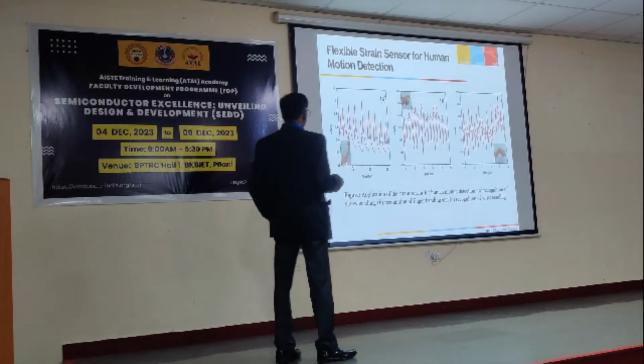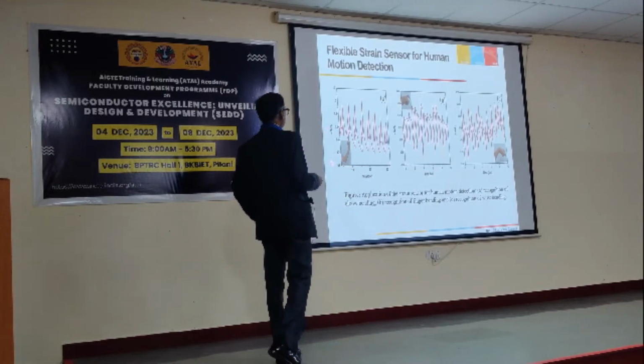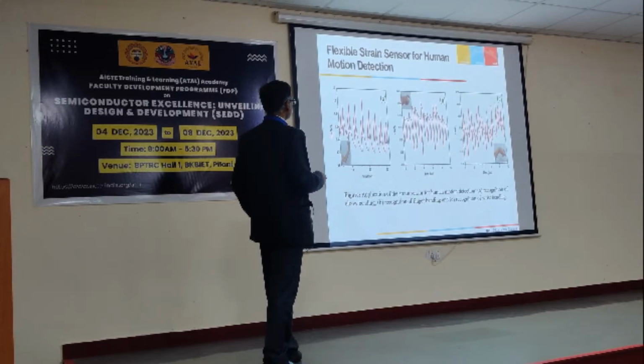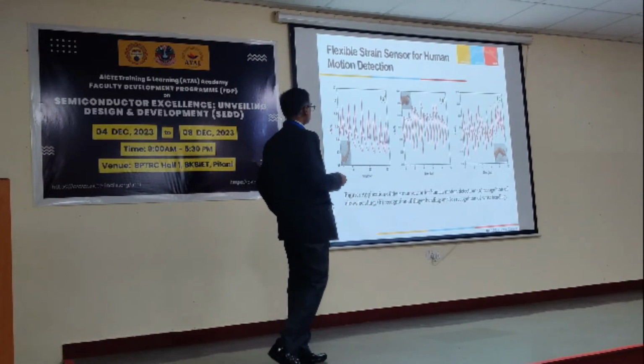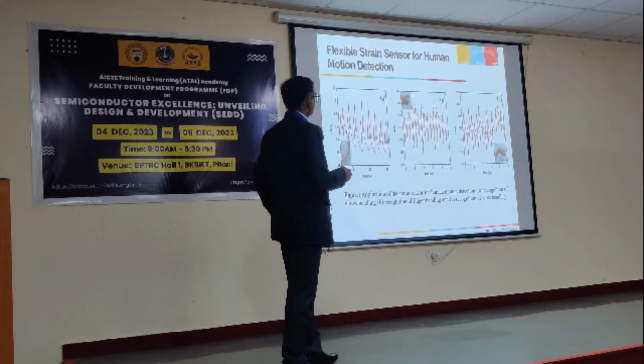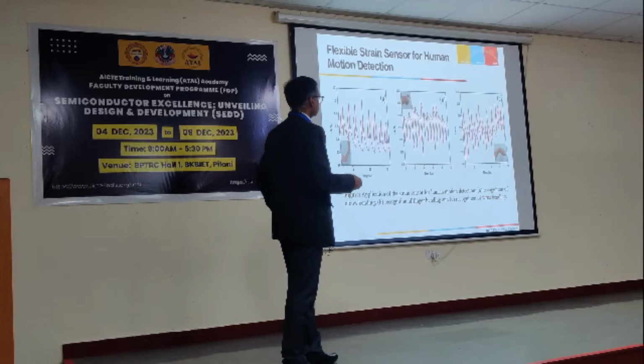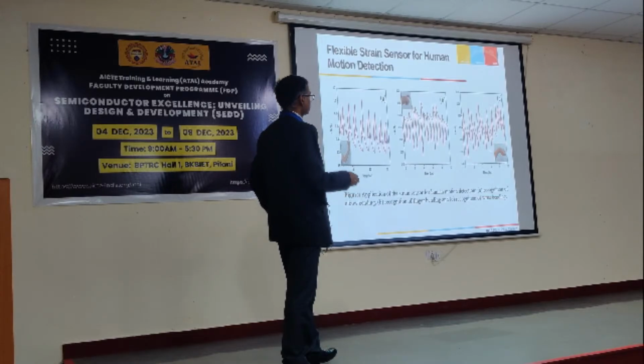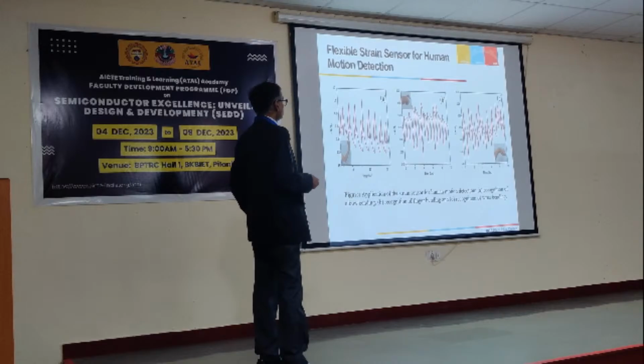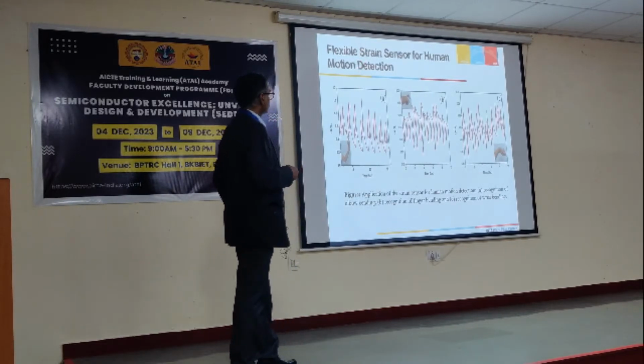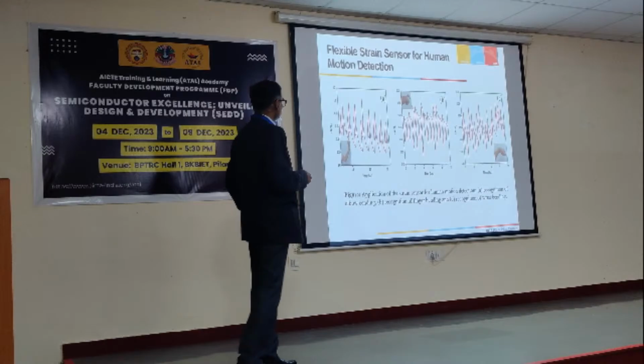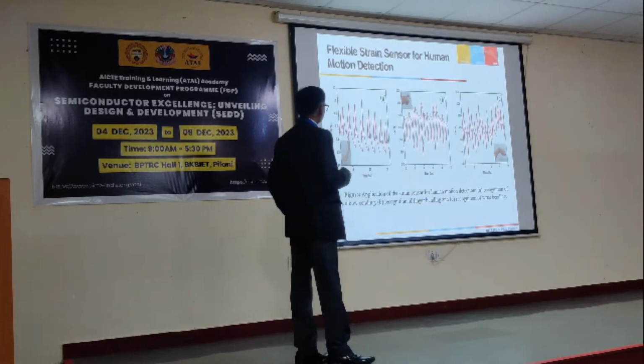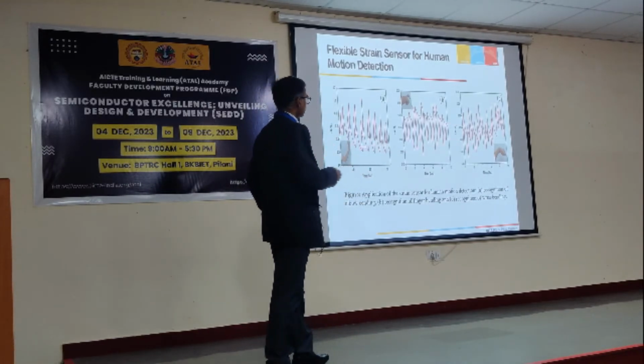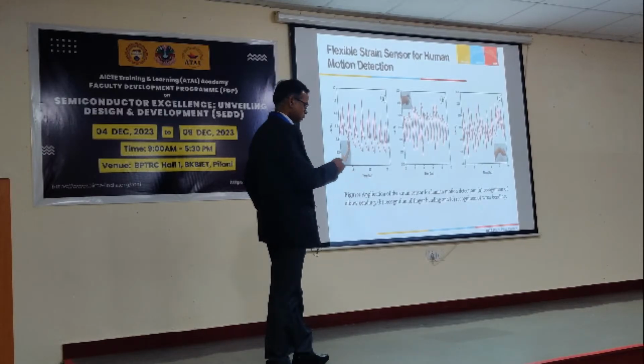So we tested by placing this on the elbow, and again with respect to time, we have measured the sensitivity, that is the change in the resistance divided by R naught, after bending the finger, and the pulse in the recognition of the wrist bending. Basically we have captured this. So here we can see that the device that we have fabricated based on graphene is going to capture the very high resistance, high stretching to the low stretching. The resistance measurement is possible within this range.